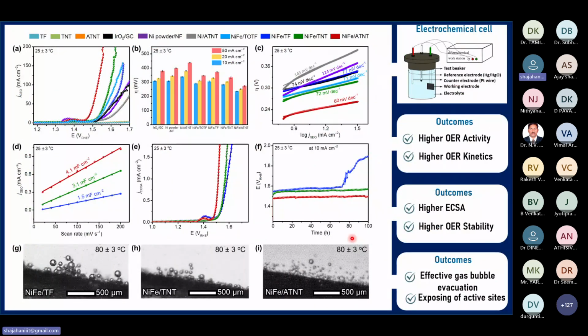Once we prepared the nickel iron ATNT electrode, we did half cell measurements initially using 1 molar KOH solution. We also compared with the remaining electrodes. From the analysis, we observed that nickel iron ATNT showed better oxygen evolution reaction in 1 molar KOH solution, better OER kinetics, better electrochemical active surface area, better electrochemical surface area based LSV, and better stability. If you see this stability, this is important, right? If the system is maintained for a long time, that is actually a benefit for hydrogen production.